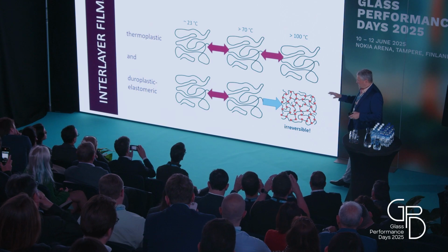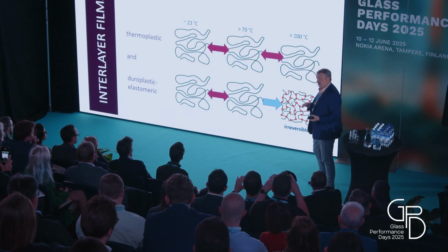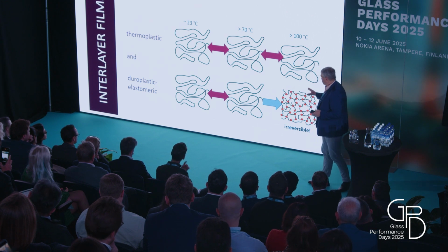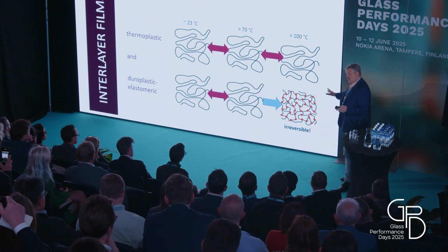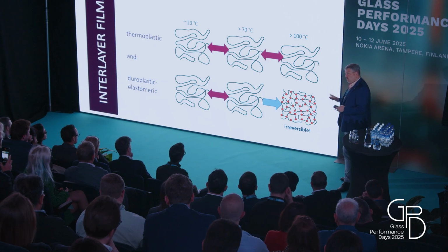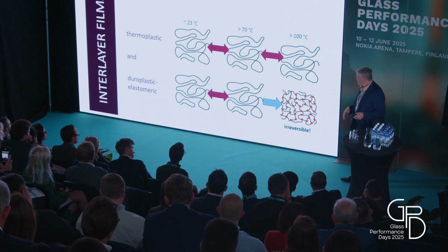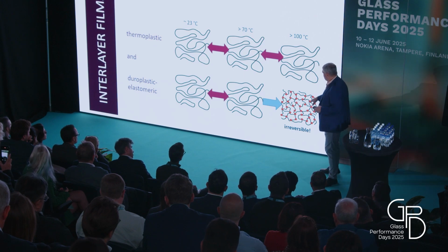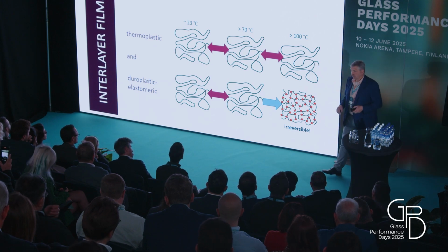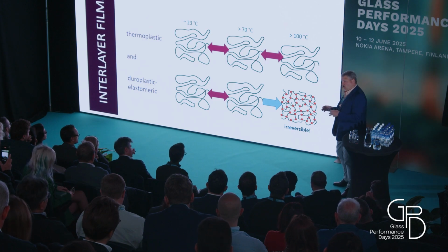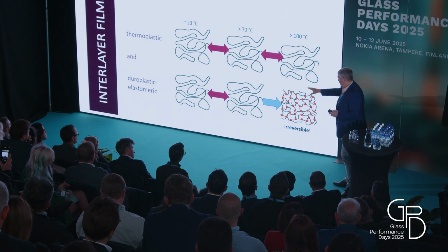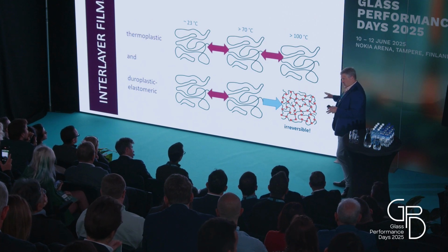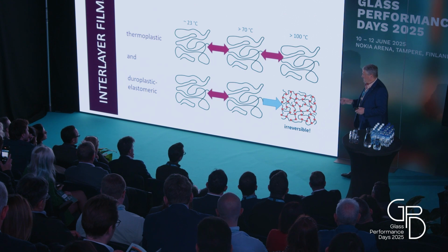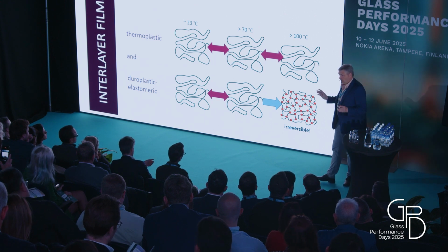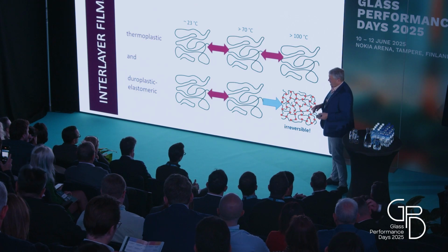Okay. In duroplastic-elastomeric, as I said, there are some additives inside, making the so-called cross-linking process and making a different thing. We need a certain temperature. It's normally, of course, the lamination temperature, as we have it in the glass industry, of more than 100 degrees C. And the additives are forming some connections between these polymer chains. These are chemical bonds, and they cannot be broken again. This means this process by heating up is irreversible, and we keep this structure of the interlayer in the glass laminate as it is. What this brings, I will show you in a second.